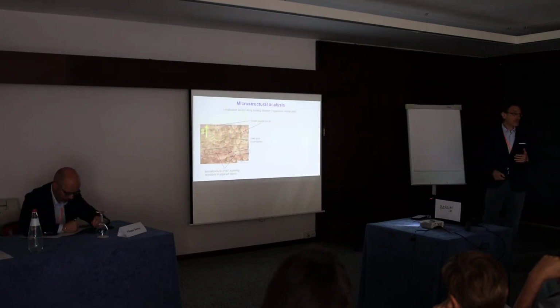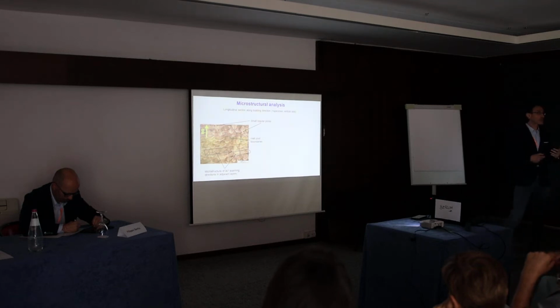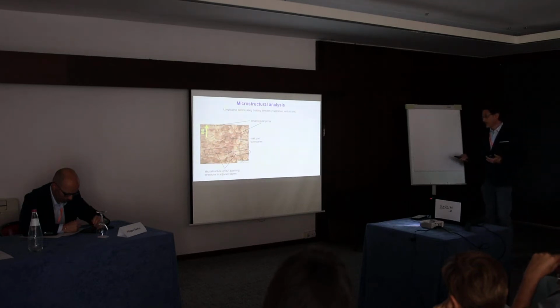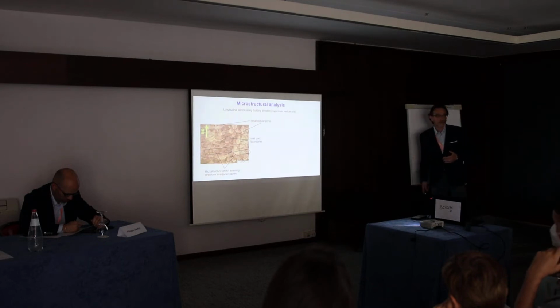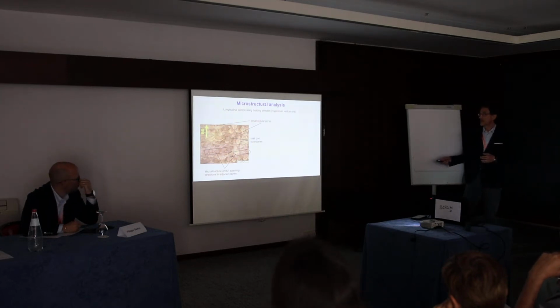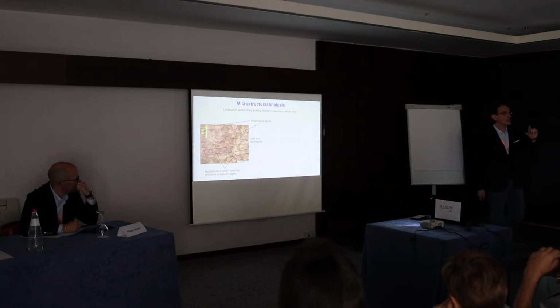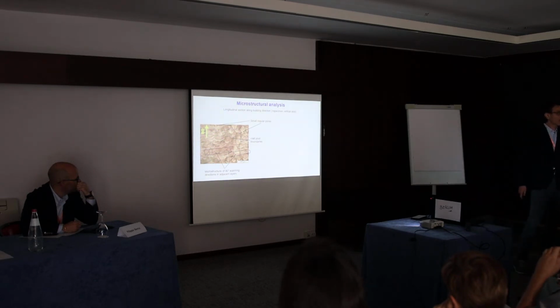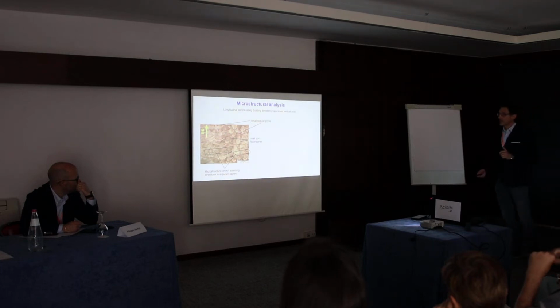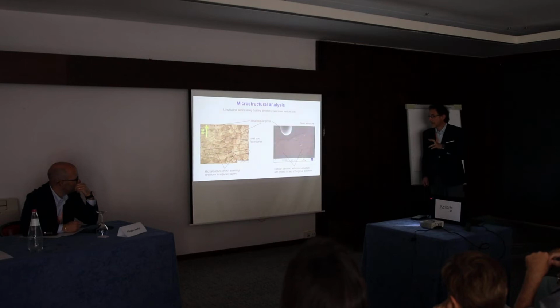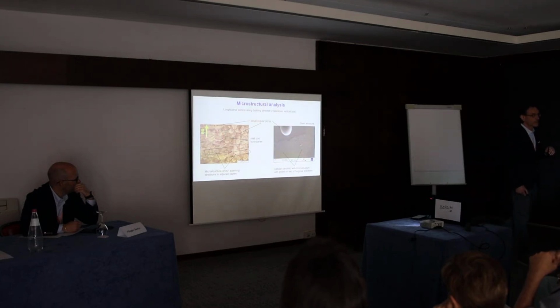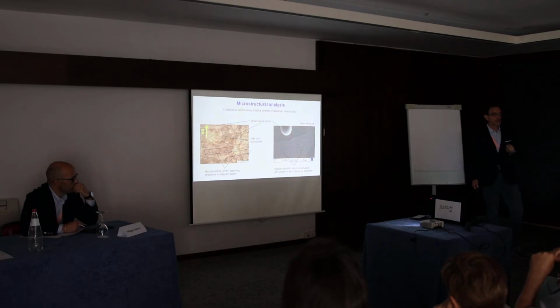Before carrying out the tests, we also performed some microstructural analysis. This is a typical microstructure of an additive manufactured material, so you can very easily see the melt pool boundaries here. There are some small regular pores, and you can also see the difference in the microstructure for adjacent layers, which are rotated 90 degrees. We also performed analysis at higher magnification in order to reveal the grain structure, which is formed by a cellular dendritic substructure with growth in two orthogonal directions.